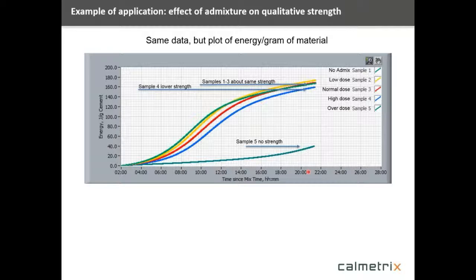If you remember from a few slides ago, we talked about the fact that the total heat evolved from the sample at a particular time is correlated to the strength that builds up within the concrete. So here you can see samples one through three, the no admixture through the normal dose, generate about the same amount of heat at a particular given time on these curves. So that means the strength is about equivalent across these three different samples. However, the blue curve, the sample that has a high dose of admixture, has a significantly lower heat output at the same amount of time. So the strength is significantly lower. So here might be an example where the high dose might be beneficial from an initial set time. As you recall, that was the highest initial set time. But you may pay a penalty in terms of strength that you're not willing to pay.